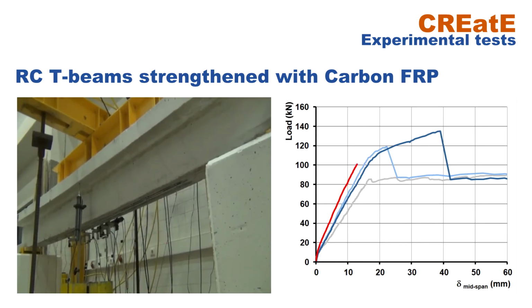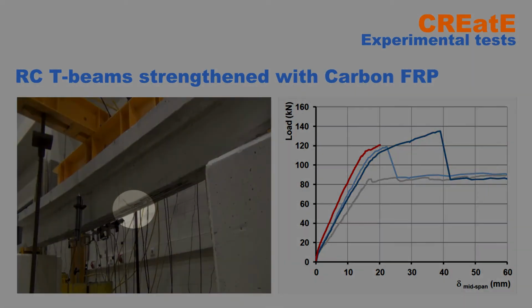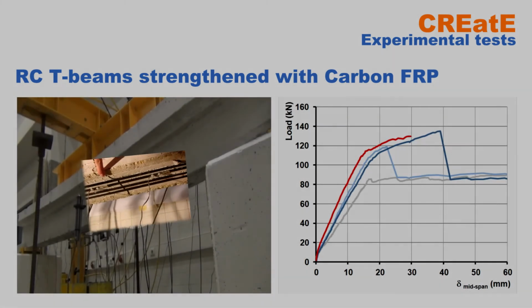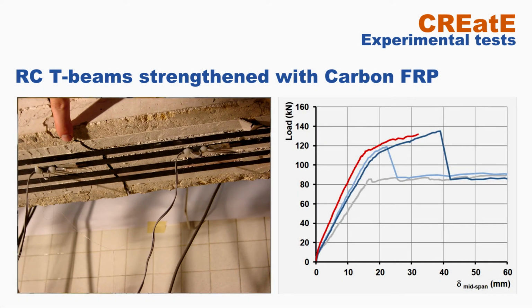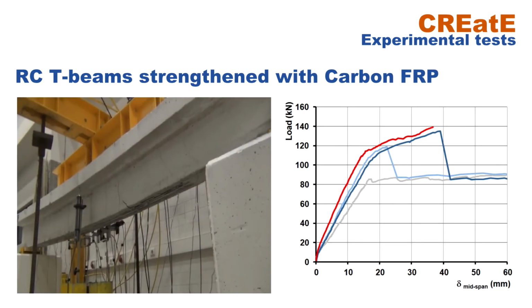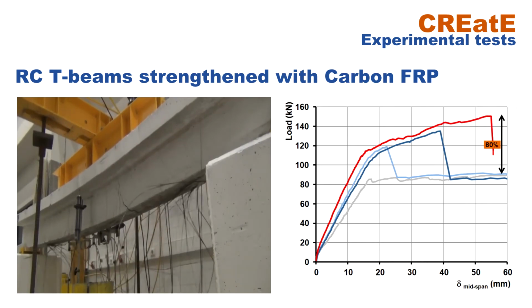The results show that the stiffness and the yielding force were clearly incremented. A zoom-in of this area shows a crack open in the concrete beam with more than 5 mm. This reveals an extraordinary performance of the CREatE system because it really avoided the bonding rupture. As shown in the graph, the strength was incremented in 80% and the ductility in 230%. The CREatE system exploited the total capacity of the reinforcement, eliminating the premature rupture observed in other techniques.